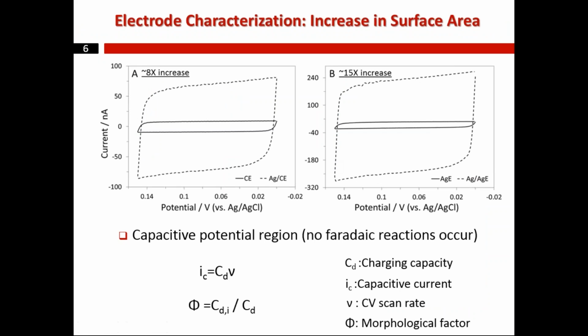Then we started to study the changes in the surface area of the electrode. When you run cyclic voltammetry in a capacitive potential regime, which means a regime where no Faradaic reaction occurs, the peak current of the cyclic voltammogram will be proportional to the charging capacity of the electrode as well as the CV scan rate. Furthermore, the charging capacity of the electrode is proportional to the surface area of the electrode. Therefore, if you compare the charging capacity of the electrode before and after modification with the silver structures, you can get some idea of how much the surface area has increased. As you can see in these two pictures on the top, for the carbon fiber electrode, we observe that this increase is 8 times, and it was 15 times on the silver wire microelectrode.